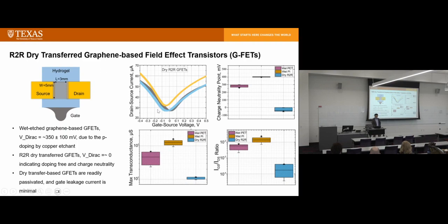We scan through the voltage. So when gate and source voltage scan from negative 0.4 volts to 0.5 volts, we measure the drain source current. The behavior is that initially you have a large current, and then when the gate source voltage becomes 0, you're supposed to see no current flowing between drain and source. So your gate and source voltage is controlling the current flow between drain and source. And you can use this shift to detect if you have a substrate or some species on your hydrogel. You can detect the species, and you can use this as a sensor.